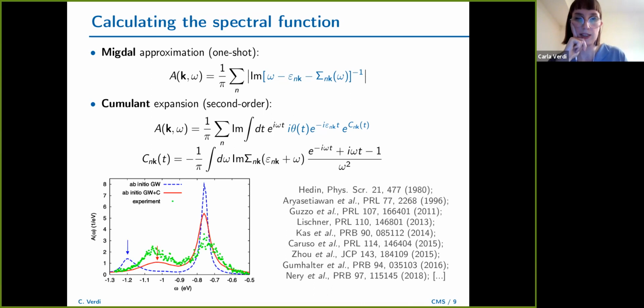And this technique has been used in many papers in the past, but mainly it concerned the description of electronic correlations. So when you want to calculate electronic correlations, you would do generally GW calculations. And if you look at the spectral functions, you can also see some satellites there. Of course, we're talking about energy scales that are an order of magnitude larger than the ones that we're looking at now. But still, you see these satellite features in the experiments. And if you do a standard GW calculation, the satellite occurs at kind of like the wrong energy. But then when you use this cumulant expansion method, the satellite is captured at the correct energy. And it's us and some other groups that recently started using this method also for electron-phonon coupling calculations.